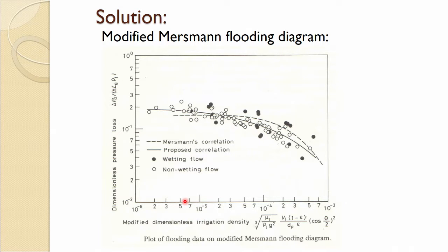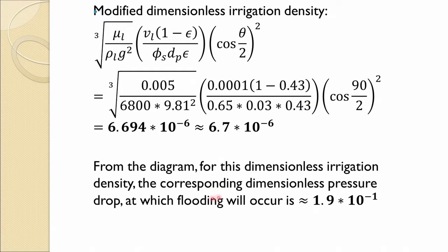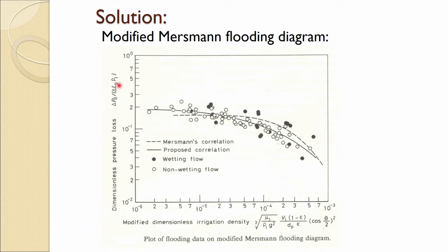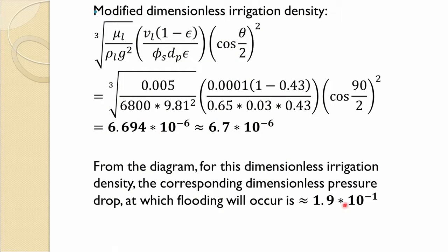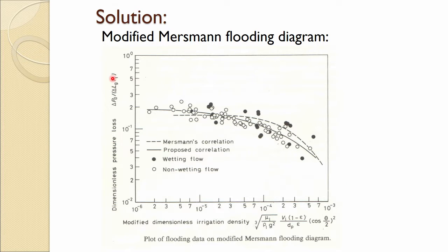So, if we look at that, 6.7 × 10⁻⁶ is coming somewhere here. So, we look at this, and this gives a flooding limit somewhere here, around 1.8 or like this. From this, if we calculate, flooding will occur if we have a dimensionless pressure drop of about 1.9 × 10⁻¹. So, now we have to check whether this quantity is close to this or not. To calculate this dimensionless pressure loss,